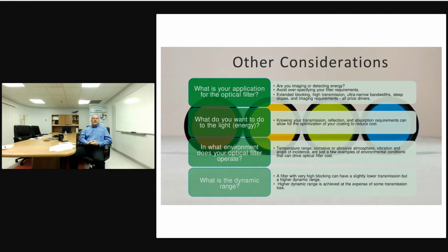Temperature is really a big one, especially for assembled optics. The thermal properties, how things are going to outgas is really critical. Not all substrates play together well. You need to find good thermal matches when you're creating your optics. Again, if you're in a corrosive environment, if you're in a hostile environment, you really need to build a robust coating, something that's really hard. And here at Innovaco, we make anything from DLC to hard sputtered magnetron coatings that would stand up to the severest environments. But again, if you don't have a severe environment, there's low cost solutions that can help you out. So environment conditions are really important to getting a great solution and for a cost driver.